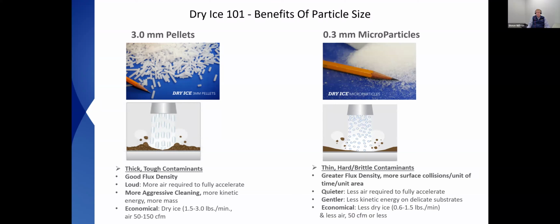You're going to get more surface strikes, more impacts per unit of time, per unit area, and it's really good for thin, hard, brittle contaminants like cleaning the mold. They're quieter because it only takes 50 CFM or less. Some nozzles only require 12 CFM, typically it's 25 to 30, and it takes about 1/3 of the amount of ice. 1.5 pounds is the maximum instead of the minimum.